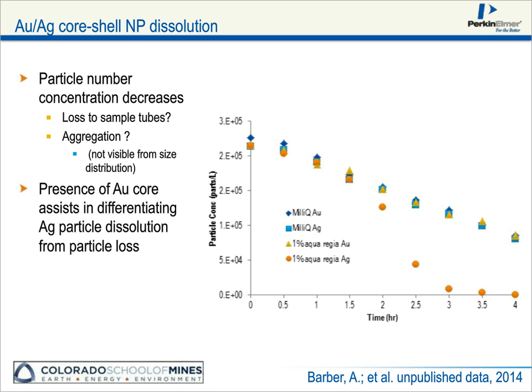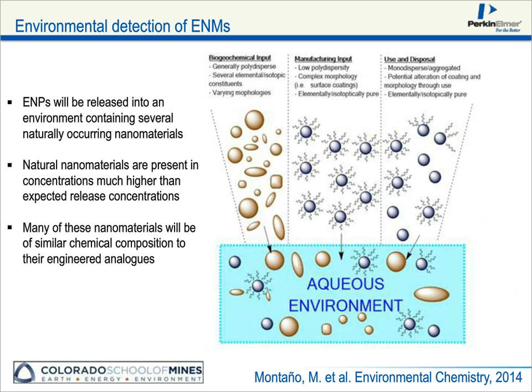Now, the other issue I wanted to address, as Kevin mentioned, is that in complex matrices, not only are we going to possibly have our engineered nanoparticles, shown in the center and right of this image, but also we have at much higher levels natural particles that are going to form a background. Our technique has to be able to distinguish between these, and this is where the elemental composition can be useful in this approach, and that we get from single particle, which we would not get from other techniques like DLS or nanoparticle tracking. So we're going to try to look at elemental composition and how that might help us differentiate the engineered nanoparticle from the background.